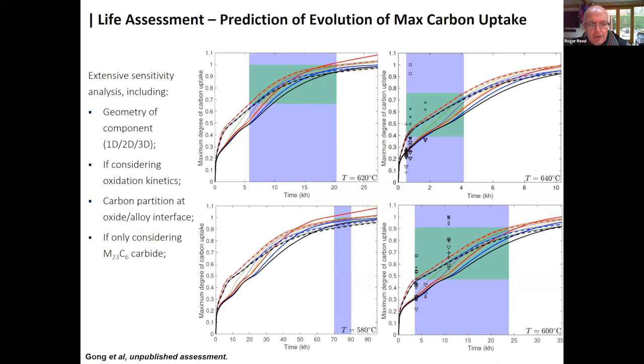And this slide summarizes our approach, which is to say that a breakaway occurs when the reservoir of metal associated with the substrate is sufficiently exhausted. The activity of carbon at the interface then approaches that of one, and then graphitization of the interface occurs, and the failure of the oxide ensues very rapidly from that point. But you can see again in science, one has to deal with scatter in data.